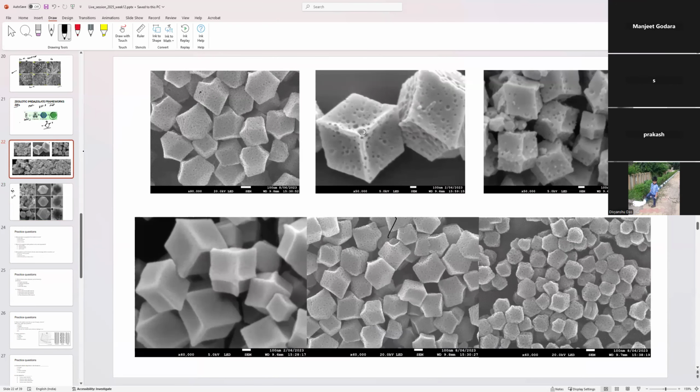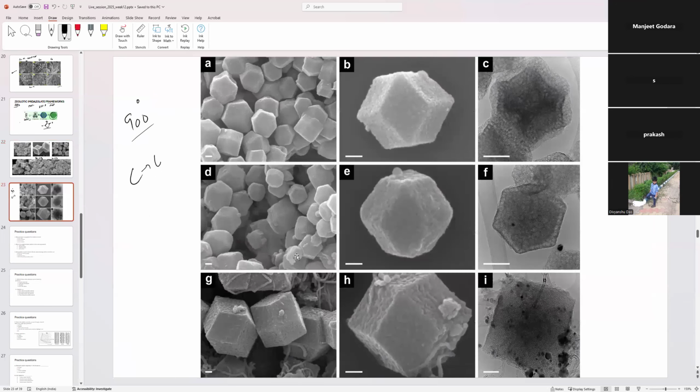This has some copper doping in it. And in this, some of the zinc is replaced by iron, so there is a zinc and iron mixture. Once you carbonize it, you get a structure with carbon and iron, or iron with copper. At 900 degrees Celsius, most of the zinc is evaporated because it boils at a low temperature. And then you get this porous carbon.